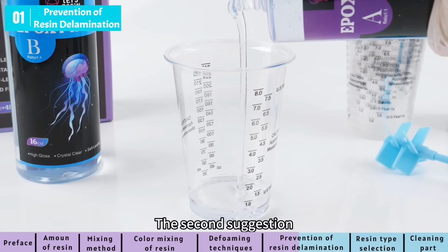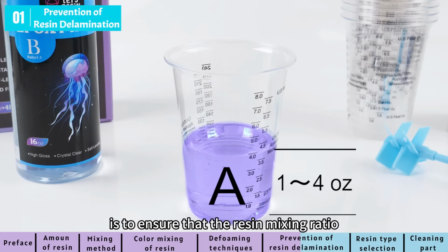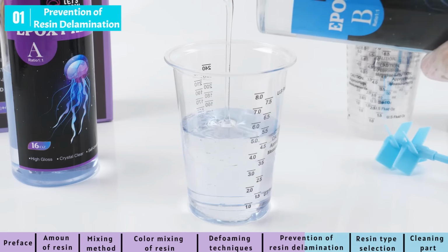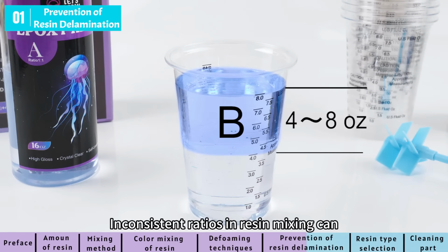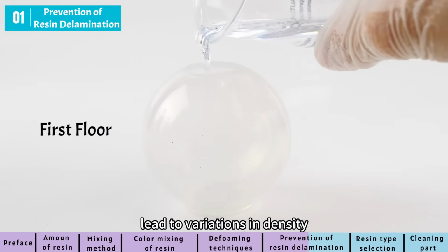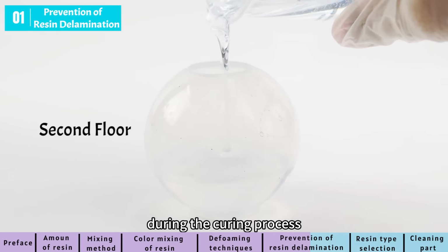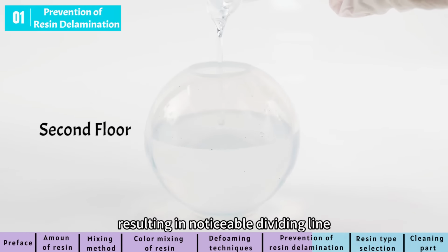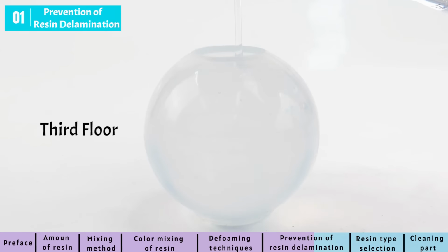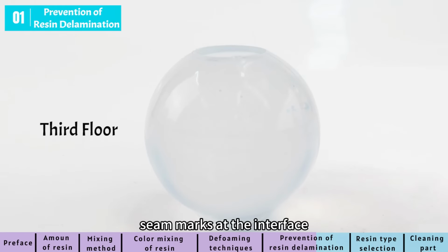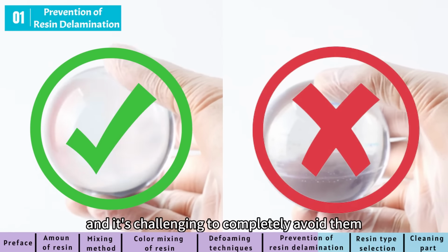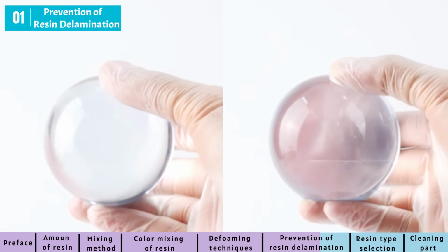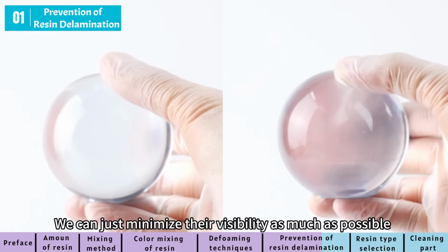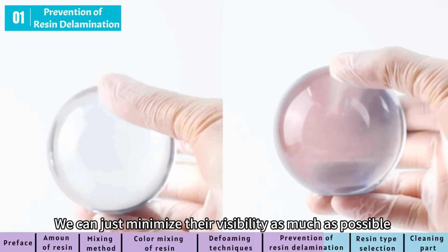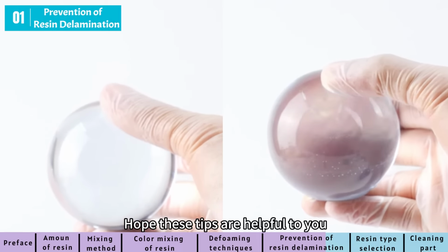The second suggestion is to ensure that the resin mixing ratio remains consistent with each layer. Inconsistent ratios in resin mixing can lead to variations in density during the curing process, resulting in noticeable dividing lines. There will always be some slight seam marks at the interface, and it's challenging to completely avoid them. We can just minimize their visibility as much as possible. Hope these tips are helpful to you.